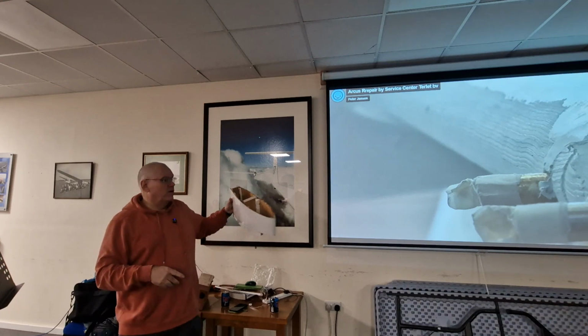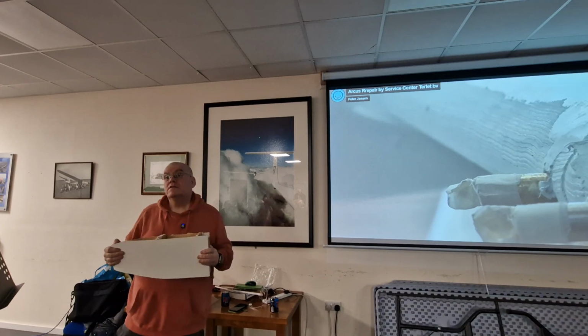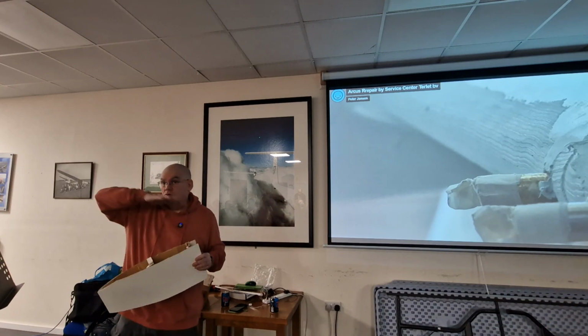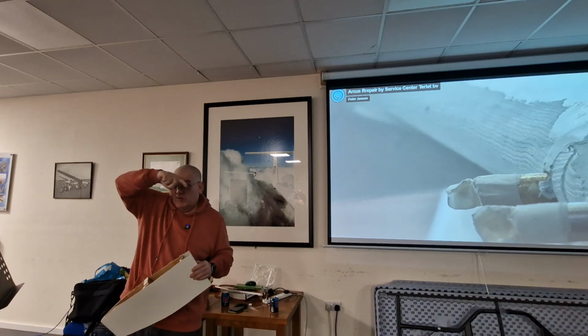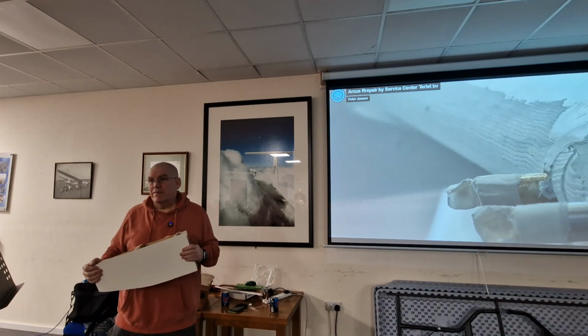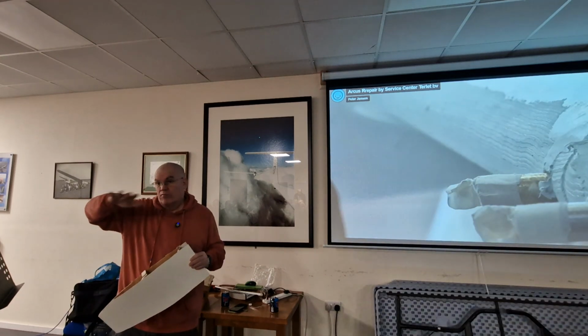It's got to be the same as the wing. Well, it'd be an epoxy resin, the one I showed you probably, because that way it will expand and contract at roughly the same rate. So it is literally a matter of just gluing it on. Yeah, you have to take the gel coat off, get back down to the epoxy cloth itself, because nothing sticks well to the polyester. They're chemically very different. But yes, you literally remove the polyester gel coat or acrylic finish, whatever it is, and bond it on.